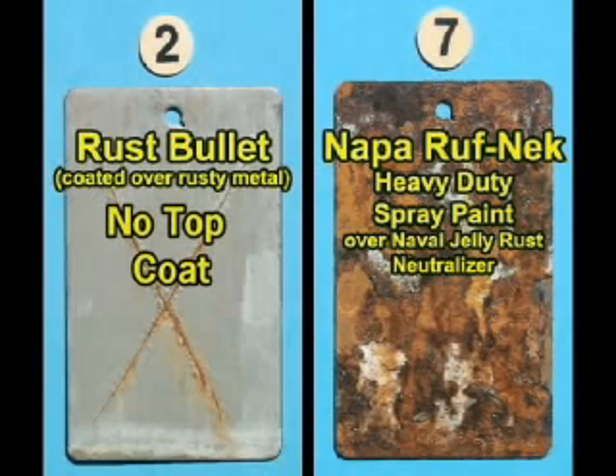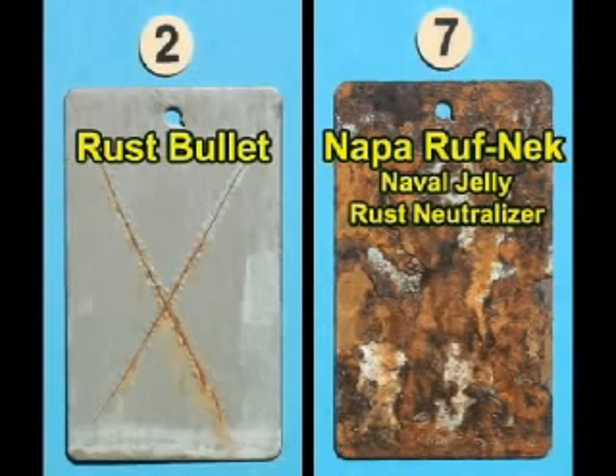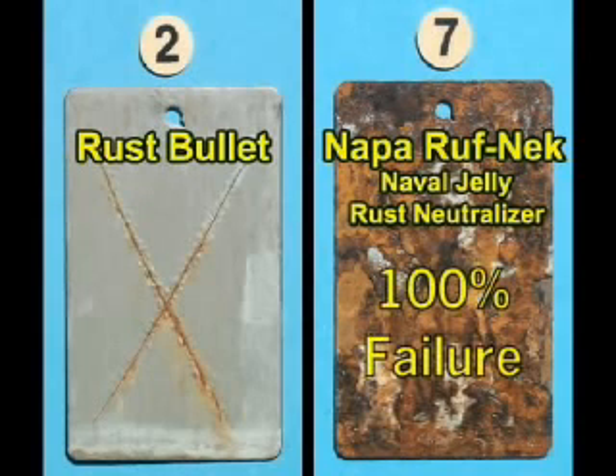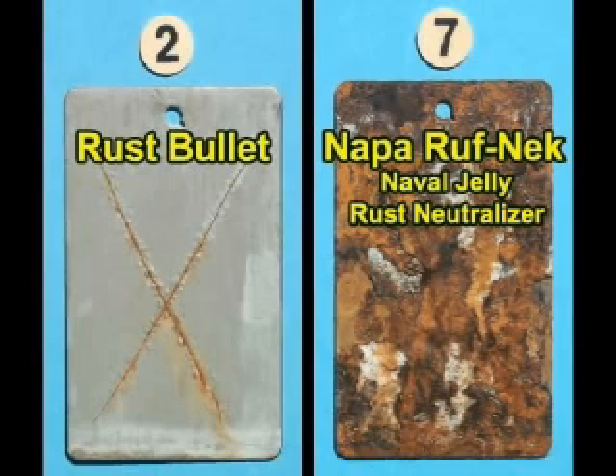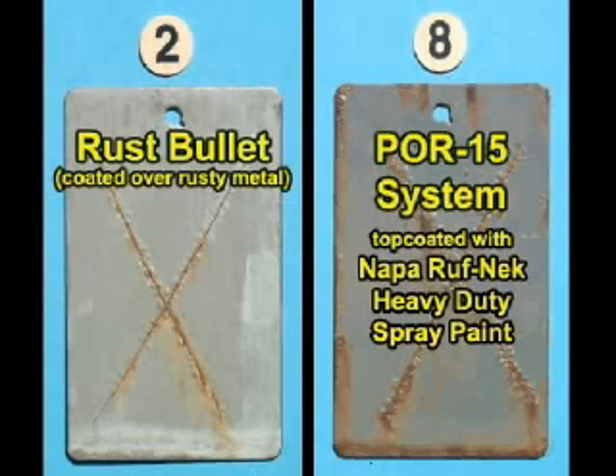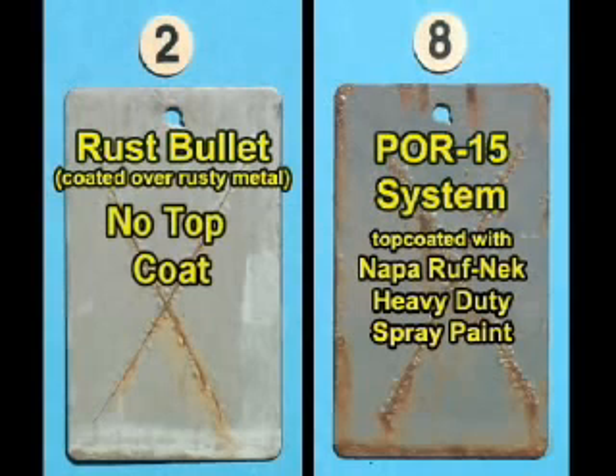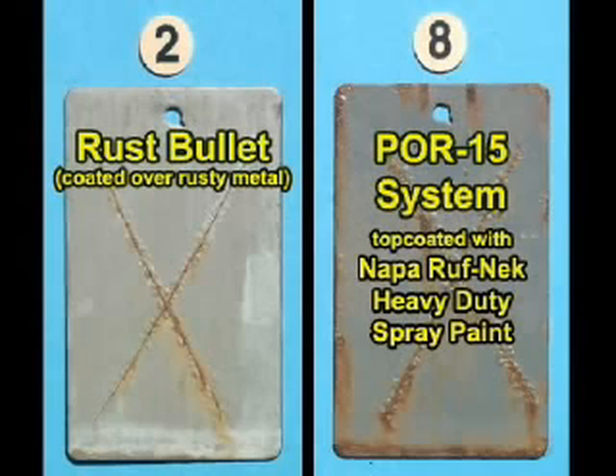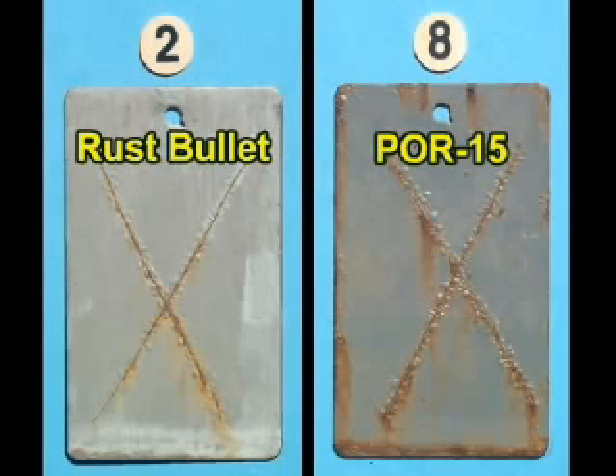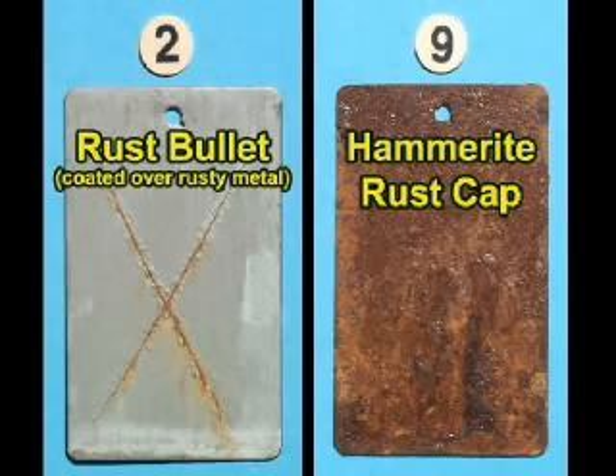This test panel is coated with Napa Ruf-Nek Heavy Duty Spray Paint over Naval Jelly's Rust Neutralizer. This coating system not only failed, but as indicated by the depth of the corrosion, it failed early on in the testing cycle. It has gone beyond the thin patina of rust onto heavy flaking and cancerous pitting. This test panel is coated with the POR-15 four-step system and top-coated with Napa Ruf-Nek Heavy Duty Spray Paint. This panel is the third best in the testing series. As you can see, significant blistering and undercutting are proceeding from the scribe lines, and there is moderate undercutting around the hole and the edges.